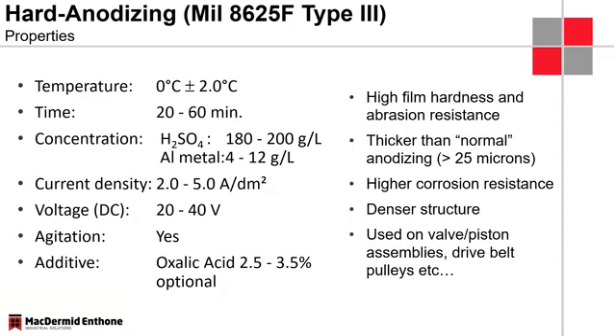So the type 3 anodizing, some people call it hard coat, hard-anodizing. The bath is similar. It's a little higher in concentration sometimes to give a bit more conductivity. But what we do here is we reduce the temperature. We bring that down to around about 0 degrees Celsius or 32 degrees Fahrenheit, and that will really give us the chance, or the anodizing tank, the chance to build much higher thicknesses.